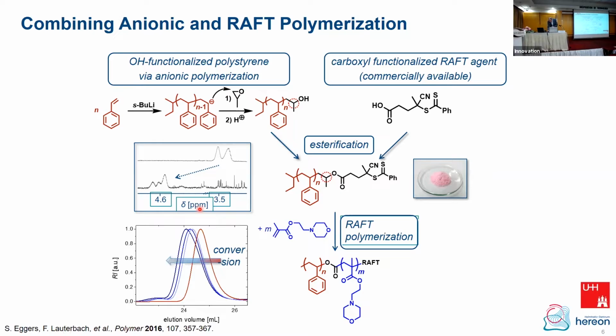So you have first the anionic polymerization in THF of styrene at low temperature. Then you add propylene oxide to end-functionalize your polystyrene with the OH group. And actually, we had a hard time first to understand certain NMR peaks, but it turned out this is the proton here, because we have a kind of stereo center and two different magnetic environments of this hydrogen. And then you add the RAFT agent by a Steglich esterification, basically. And that's the last step. You polymerize the methacrylic monomer as a second block. And the conversion you can follow by NMR, and you see in the GPC also that you get an increase in molecular weight and keep quite nice control. And the typical color of this RAFT stuff is this pink color in this case.